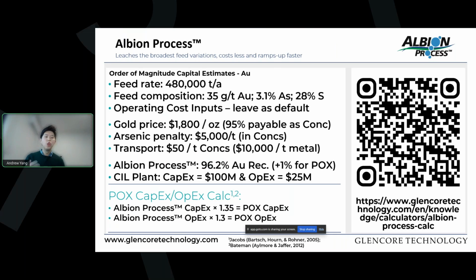So the reason for that is, as I mentioned, POX is a much more intense process. So it's at high temperatures and high pressures. And what it does is it melts away typically all of the sulfides. So when you melt away all of the sulfides, you are able to extract all of the contained gold. With the Albion process, we pride ourselves on being able to optimize the grind size, and we only grind as much as we need in order to get an economic amount of recovery there. But I am acknowledging that POX does have a high recovery.